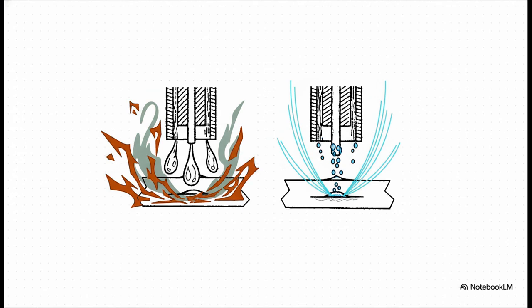Believe it or not, the shielding gas you choose has a massive impact on how the metal gets from the wire to the workpiece. If you're using a gas rich in CO2, you often get what's called globular transfer. Think of it as big, clumsy drops of metal falling into the weld. It works, but it's messy and creates a lot of spatter. But switch to an argon-rich gas, and you can achieve a beautiful spray transfer, a fine mist of tiny droplets that are literally projected across the arc. The result is a much cleaner, smoother weld.